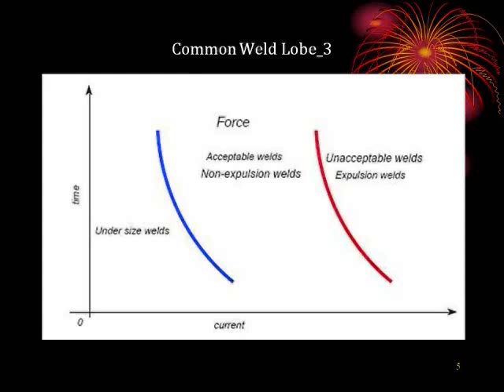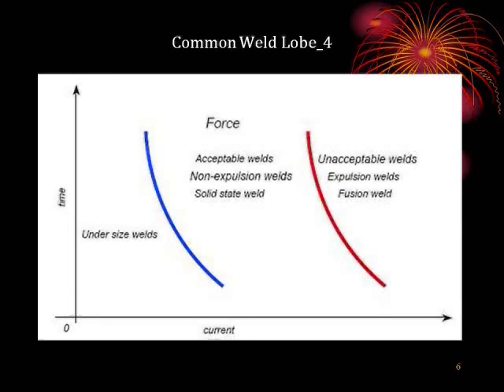If we add more description to these two curves, on the left hand side of the right curve, since the other side is an expulsion weld, the left hand side has to be a non-expulsion weld. Since the left hand side is an acceptable weld, the right hand side has to be an unacceptable weld. We can add two more lines of description on this weld lobe. The expulsion weld is a fusion weld, so we add fusion weld right underneath. If the right hand side of the red line is fusion weld, the left hand side has to be solid state weld.